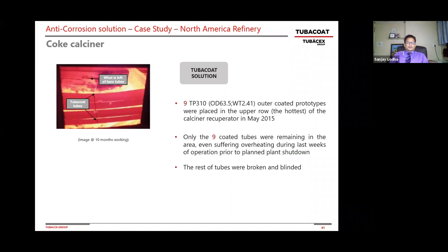So what you see here is we supplied nine TP310 tubes, outer coated, in this recuperator heater. They were installed in May 2015, now almost five years ago. After 10 months, when you look through a furnace window, you see the uncoated tubes are completely broken and blinded, whereas the TUBACOAT tubes, all nine of them, are fully visible, even after suffering overheating at temperatures close to 1500 degrees Fahrenheit. The results were so encouraging that they decided to go for a full commercial run, which I will show you in the next slide.